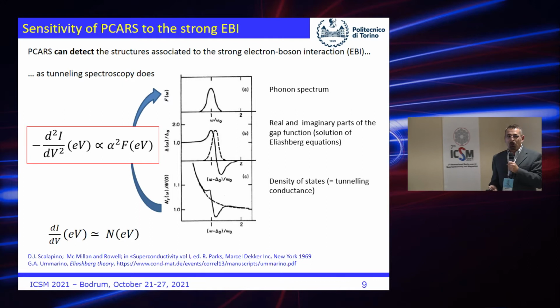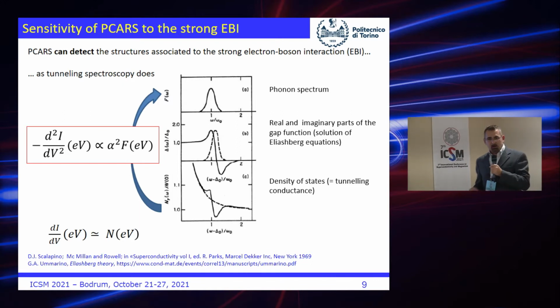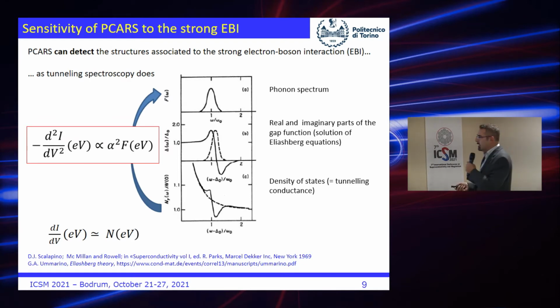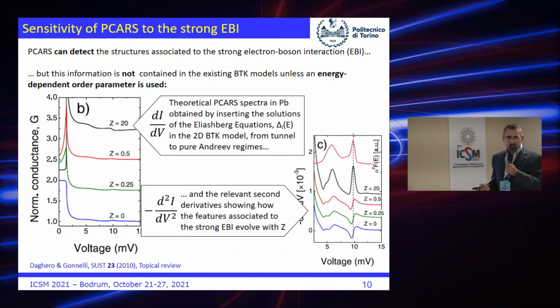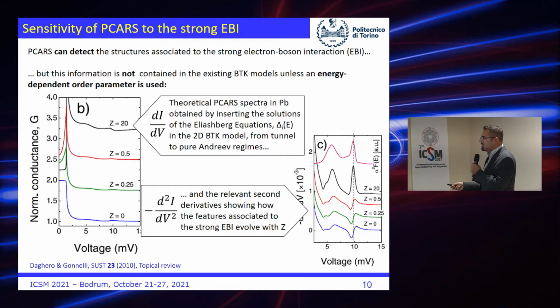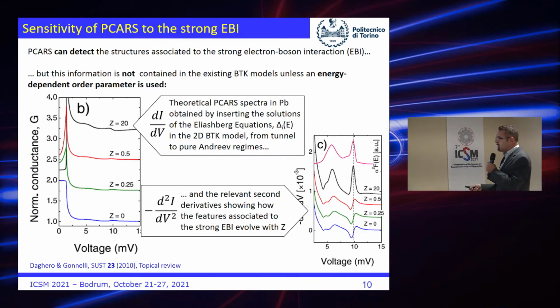Does this work only in tunneling, or does it also work in the regimes where we have Andreev reflection, so low barrier? It works also in the case of Andreev reflection. Indeed, these are the spectra for lead, that means the tunneling conductance, calculated for different values of this Z. Z is a measure of the height of the potential barrier.